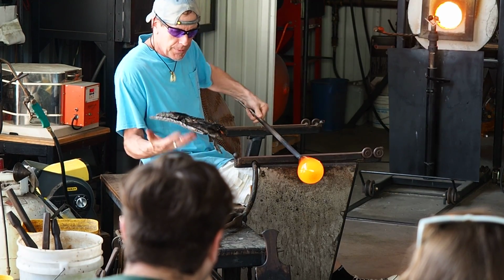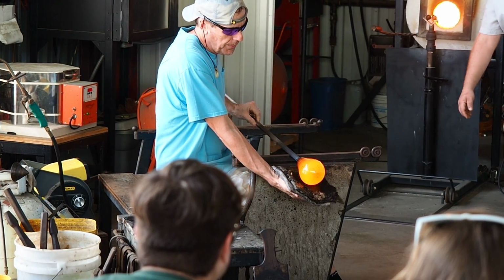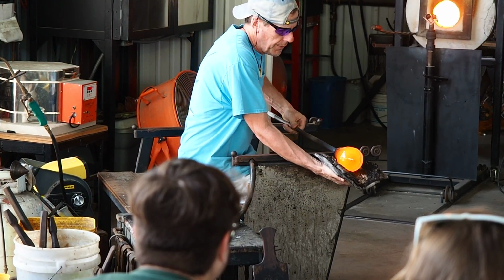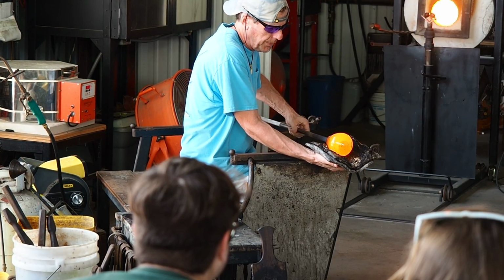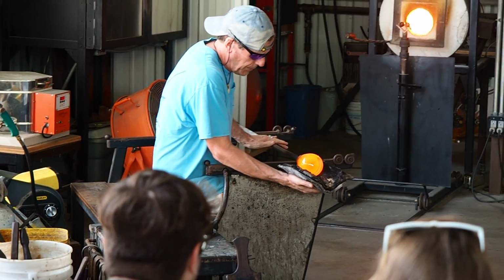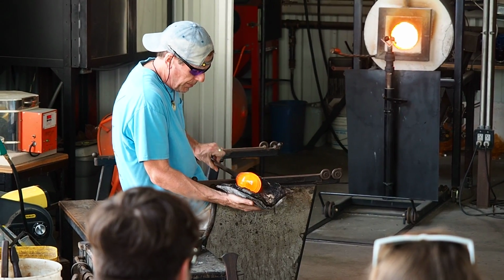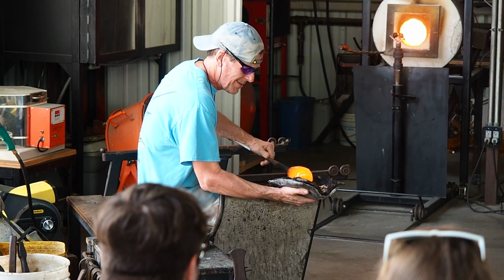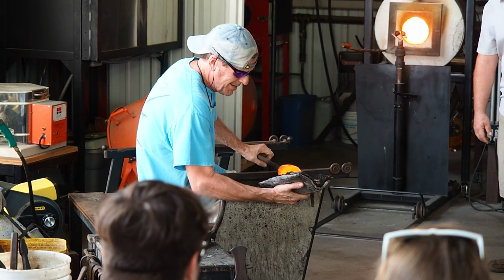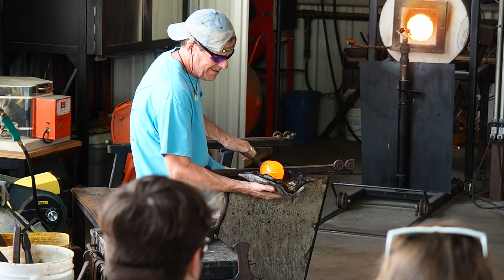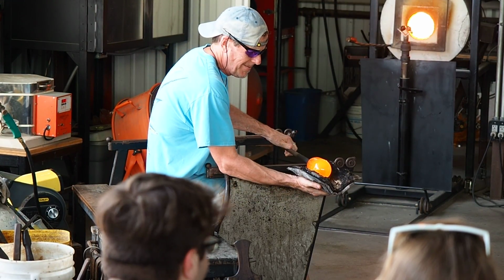This results in a little steaming phenomenon known as the Leidenfrost effect, whereupon introducing that 2,000 degree ball of glass into that wooden block, it immediately sucks the moisture out of the grain structure in the form of a layer of pressurized steam that ball of glass rides on, and it doesn't actually come in contact with that wood.